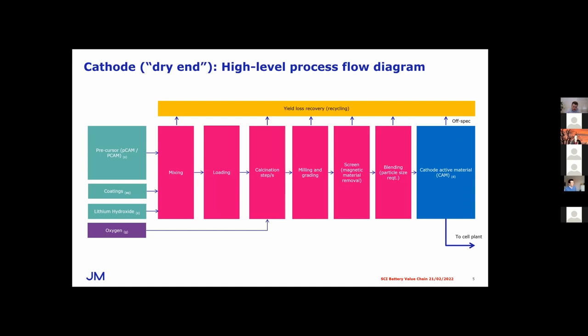In the final step of the cathode material production, this is where we bring in our precursor from the last slide, together with various coatings and then your lithium. And those products are mixed, loaded into refractory saggers, and then subjected to calcination at high temperature, where you convert your hydroxide to oxide and your lithium becomes incorporated into the cathode material. You would then mill and grade that product because typically it would come out as agglomerated, screen it for any magnetic impurities that have come from various stages of the process, and then blend it if you're seeking to create a product that maybe has a variable particle size or specific particle size requirement from the customer. And this is what forms your cathode active material, or CAM, as it's quite commonly known in the industry. And that will go off to the cell plant.